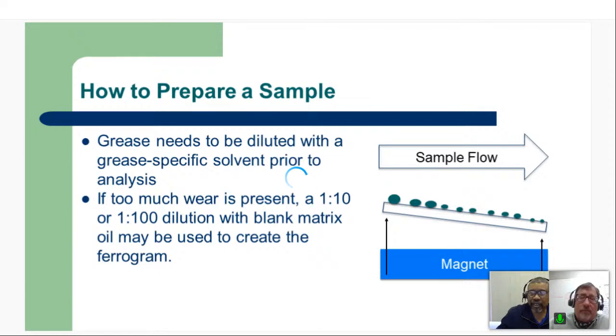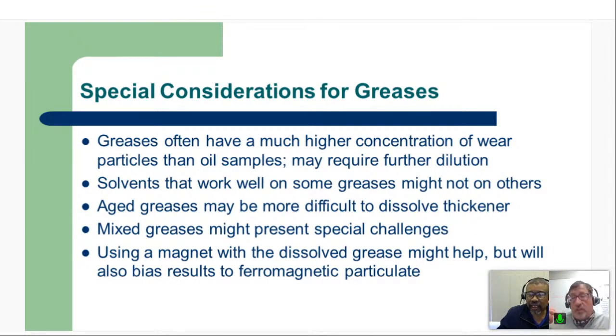That's correct. So these special considerations for grease: I mentioned this. Sometimes greases have a much higher concentration of wear particles than oil samples just because they're cumulative, right? Between replenishments of grease, the particles are being generated. They're not settling out to the bottom. They're not being filtered out like you might have in oil. So there tends to be fairly high concentration in a lot of applications. And then you've got some solvents that work well on most of your greases, and then this grease comes along and it's just not getting dissolved. Yeah. And you go and make a slide and look at it and you just can't see the particles. They're hidden behind clumps of grease or clumps of thickener, and that can be a problem.